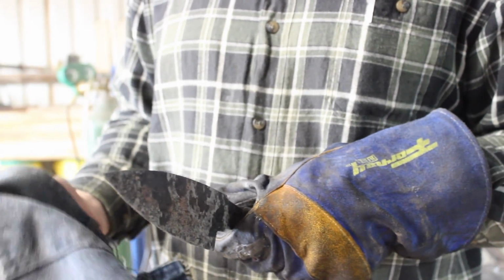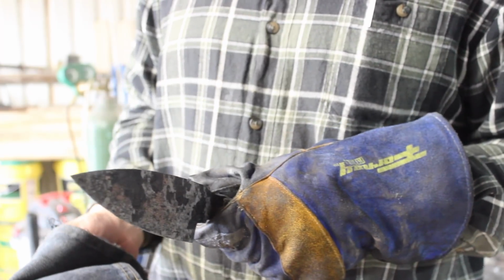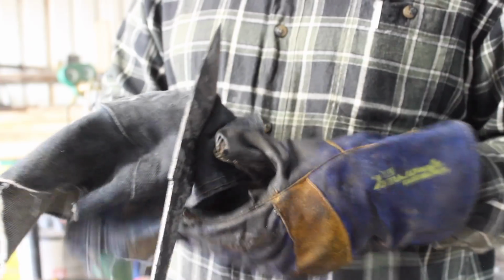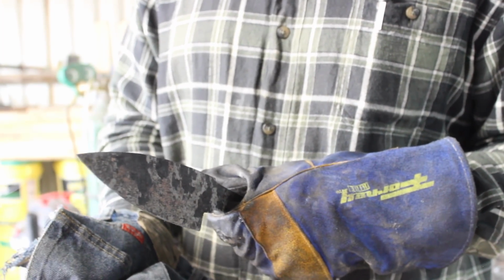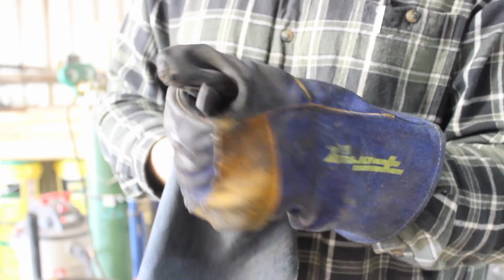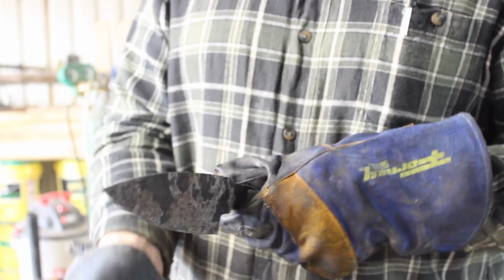So none of these blades came out perfectly straight out of the quench. They were fairly straight, which is a testament to our normalizing procedure, but not completely. And that's quite common, but it's not a big deal if you use this method that I am here and carefully straighten your blade and keep an eye on it as the temperature comes down closer to room temperature and as the hardening process completes itself. The transformation of the steel completes itself.